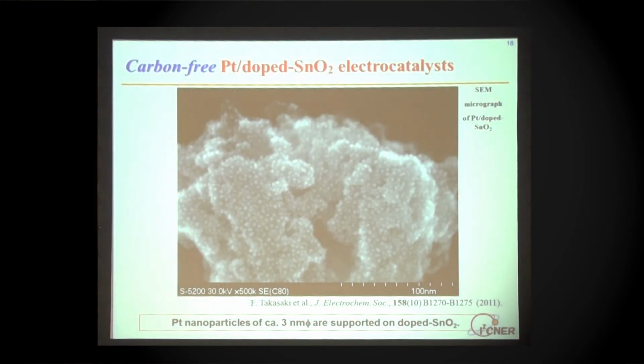And that was the way that we developed at the beginning of the I²CNER project. Now we have very small particles of platinum, of course with a diameter of something like 3 or 4 nanometers. But in this case we use absolutely no carbon. That means that the material behind is tin oxide, a non-carbon material, which also has very good electronic conductivity.